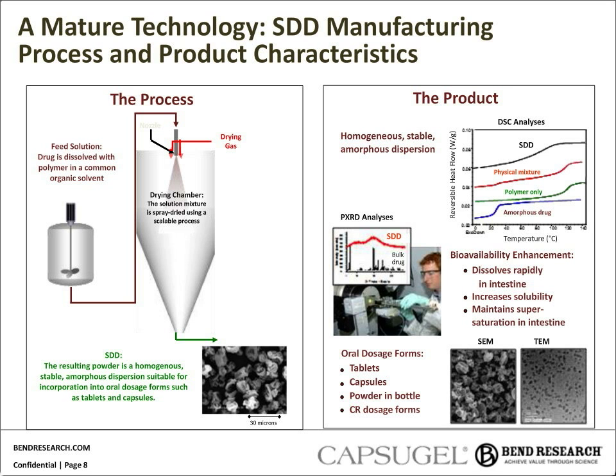But essentially, we're looking for a homogeneous system where instead of having two amorphous glass transition temperatures, we now see a composite single Tg associated with that homogeneous system. And in that case, we're looking for: does the formulation dissolve rapidly? Does it supersaturate relative to crystalline? And can we sustain that supersaturation? And then looking at how to put that drug form intermediate into the appropriate oral dosage form, be it a tablet, capsules, or even powder in a bottle, are appropriate.